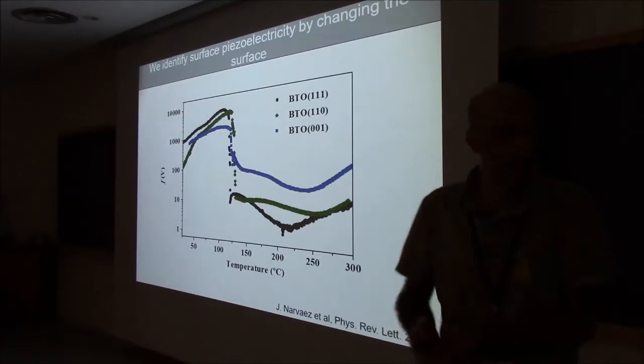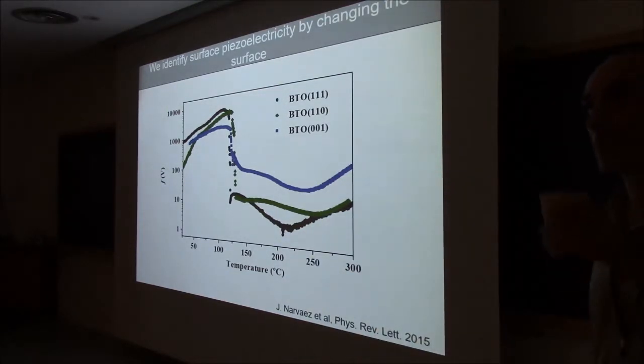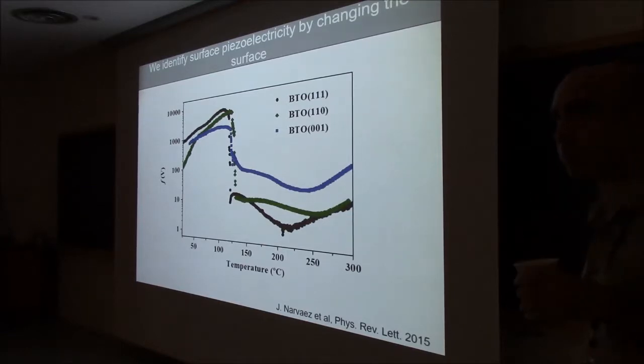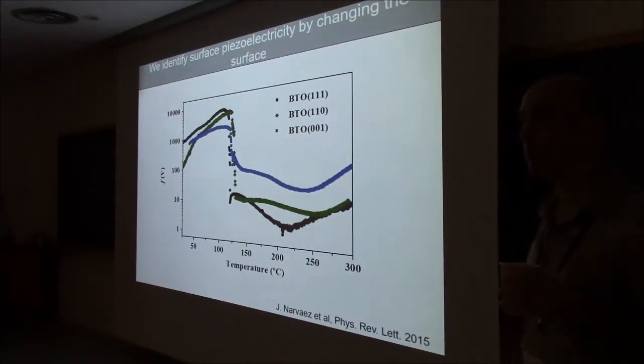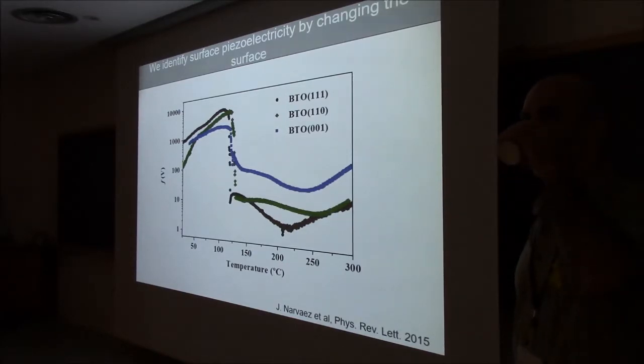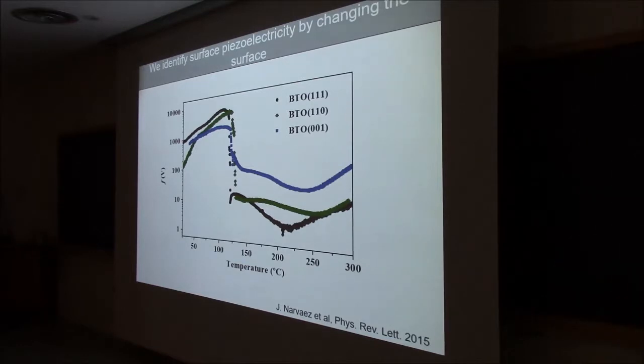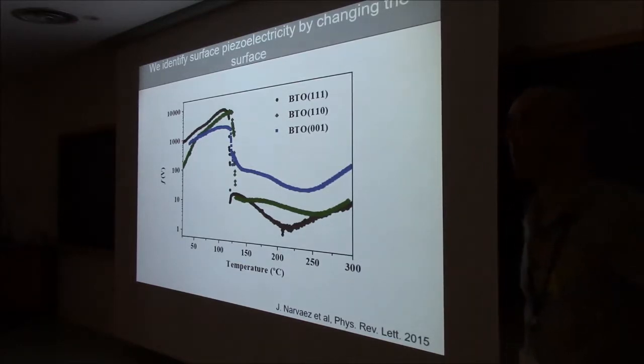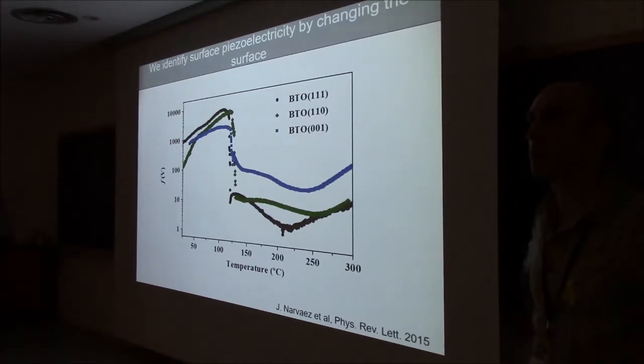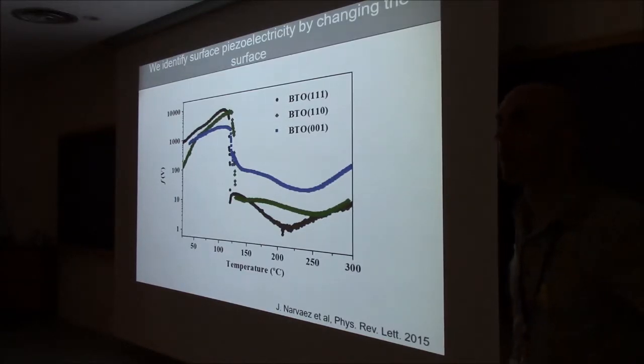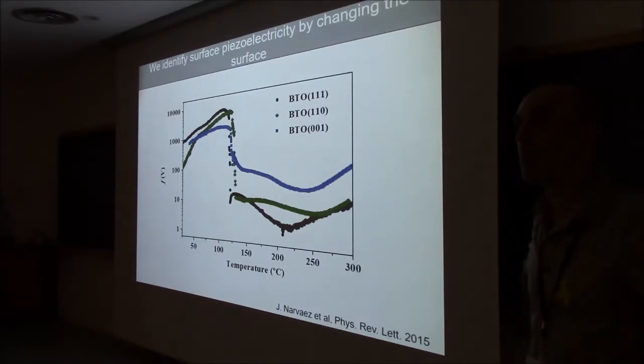Can I make another comment? Please. Just to give a different perspective on this. What you're talking about is basically the surface dipole layer. That's really the same thing as the work function of the surface, the difference between the electrostatic potential inside and the vacuum outside. And the problem is that the work function of the surface depends on the strain. If you strain it, it changes, and that gives this. It's another way of looking at the same effect. So one way of answering the question is, if you could somehow find some surface preparation that has the property that if you strain the surface, the work function doesn't change, then you would get rid of this surface piezoelectric contribution. Cool. Thank you. I don't know how to do that.